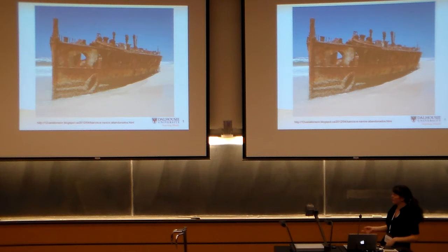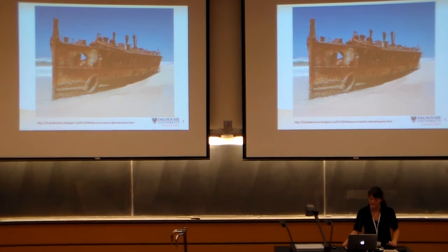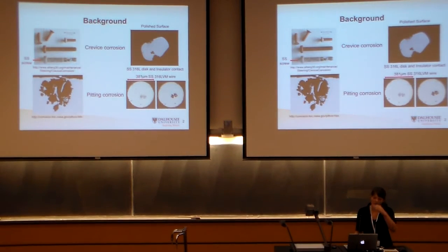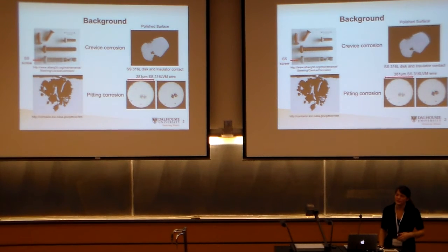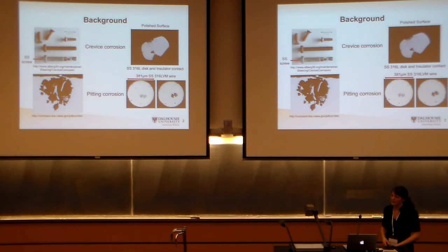Others lead to catastrophic failure, as you can see in this image here. So we work with stainless steels, which are designed to resist general corrosion. However, they're still susceptible to localized corrosion, such as crevice or pitting corrosion. Crevice corrosion occurs when the metal is in contact with another material. As you can see here, the stainless steel screw has been completely destroyed by crevice corrosion.